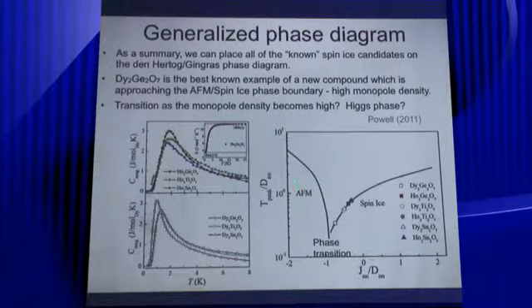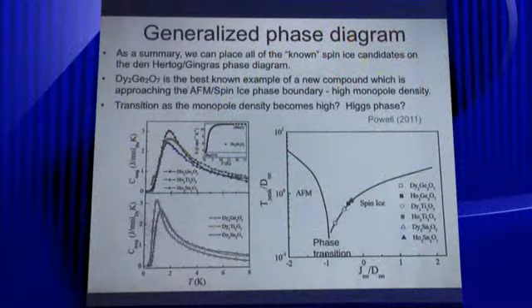So we can now put these on the Den Hertog-Gingras phase diagram, and I plotted this on log scales to see the details a little better. So these are the known spin ices except for dysprosium germanate, right? So dysprosium germanate has different J constants, lower chemical potential, and you're really approaching this phase transition with dysprosium germanate to this no man's land. I'm trying to figure out what's there. Now, it should be like a first order phase transition here, but we don't know what happens in this region.